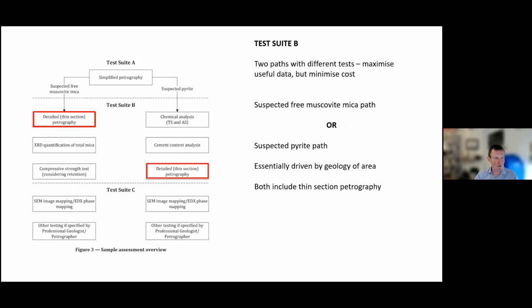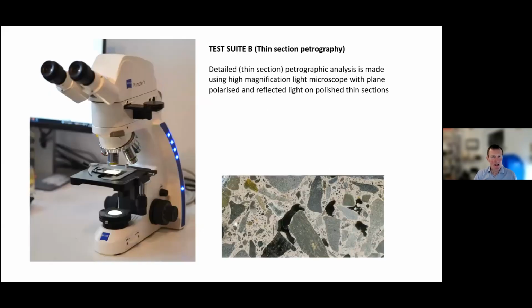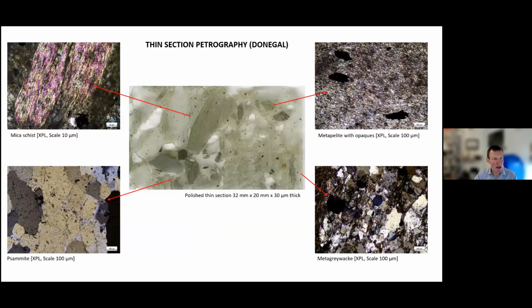So this has two different pathways, one for free muscovite mica on the left, and the second for suspected pyrite on the right. They share a detailed thin section petrography. Detailed thin section petrography is using a different type of microscope, a much higher magnification, and it has both plane polarized light and reflected light. And you use thin sections, which are 30 micron or 0.03 millimeter thick slices of rock that are highly polished. And the level of detail we can see in thin section petrography is much higher.